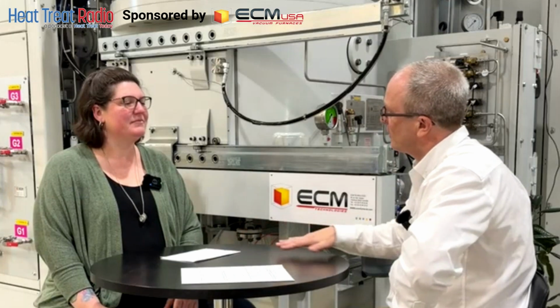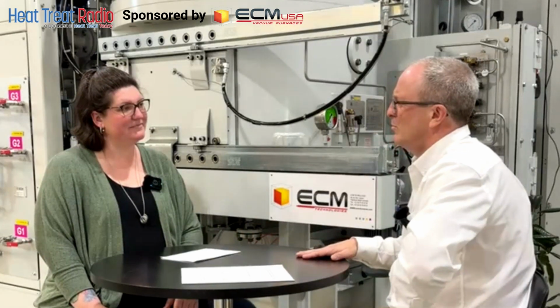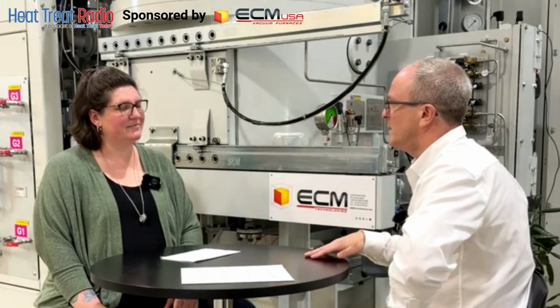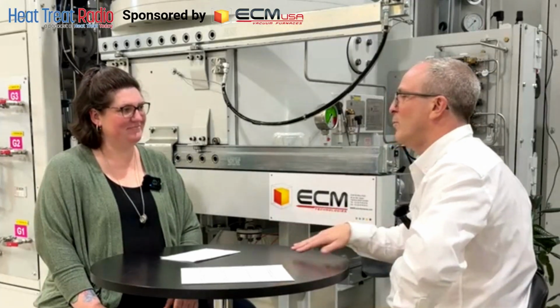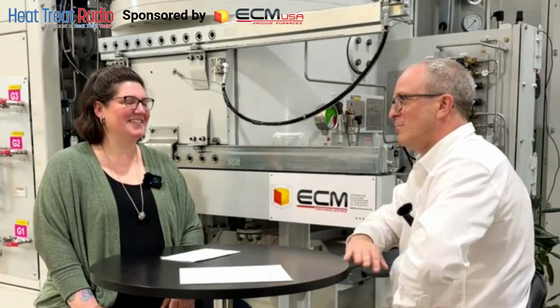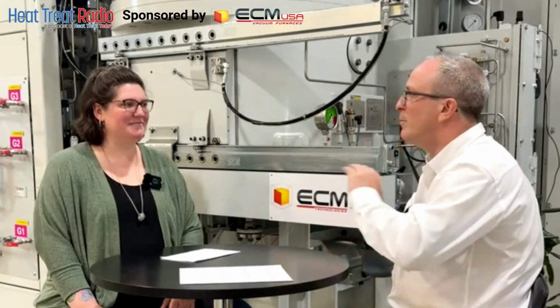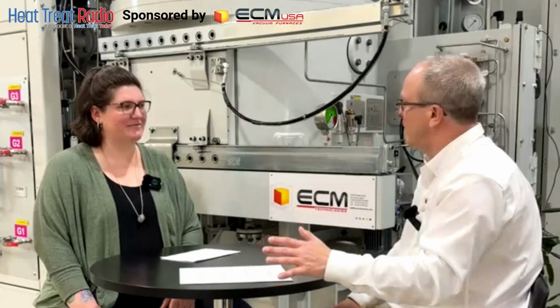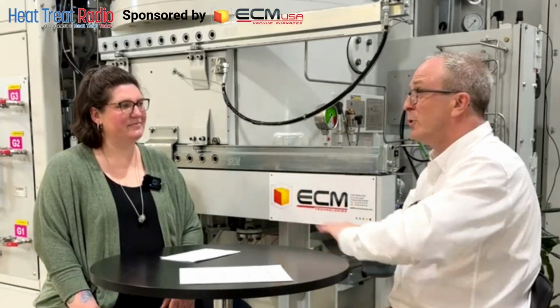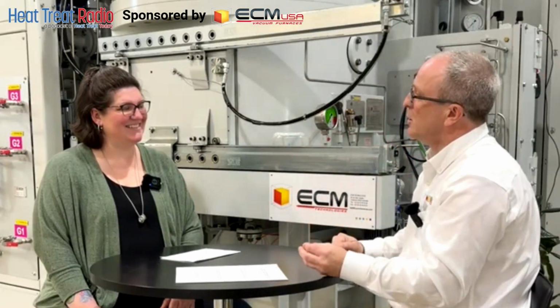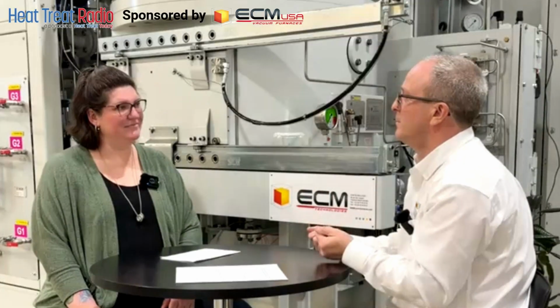We have some, I will not say names, but there are some companies that make vacuum carburizing software where you need to know everything about the steel, the chemistry and everything. We work with carbon. So you put in the carbon content originally, roughly, the temperature you would like to heat treat, and what you would like on the final. The software will give you something, and it will be good at 95%. Now, of course, you need to quench. Like I said, oil quench, no problem. Gas quench, 20 bar, no problem. Pretty easy, straightforward, you get it. Optimization is where maybe it's more tricky.